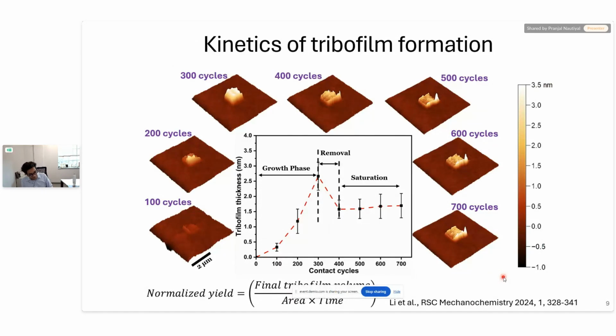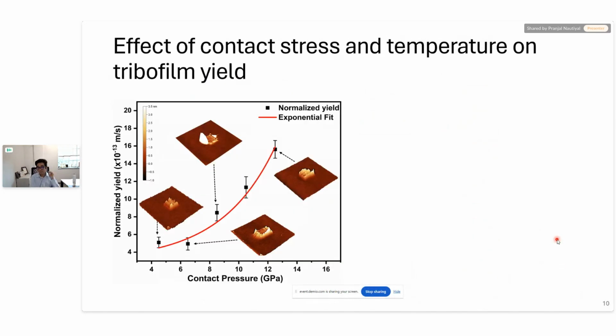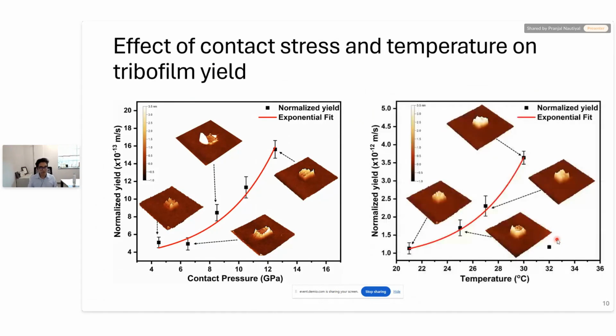We studied the yield of film as a function of stress and temperature. So we observed that the yield of tribofilm increased exponentially as we increased the applied contact pressure up to a certain point, that was about 12.5 gigapascal. Further increase in stresses did not promote film formation, but rather we saw some wear or removal of tribofilm because of severely high stresses. So these results show that the growth of tribofilm is promoted by stresses up to a critical point.